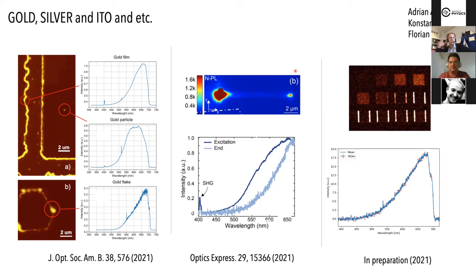You can excite basically the Fermi gas to an elevated temperature in many systems. And here I show you, of course, different gold again, but in different forms. So here you have a nanoparticle of gold and you have the corresponding spectra. Here you have a rough film, the corresponding spectra. Here you have a single crystal flake of gold, and you also have spectra. Spectra are all differing, of course, because there is this underlying local density of states that must be taken into account, but it's still all reminiscent of a decaying tail in the visible part of the spectrum.